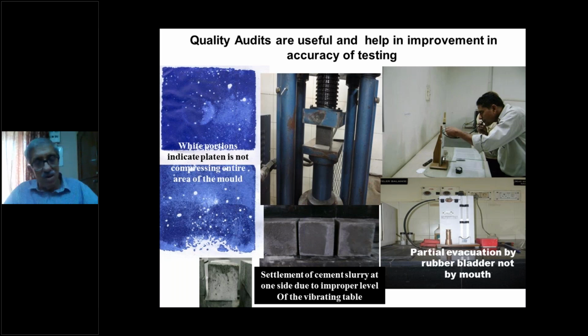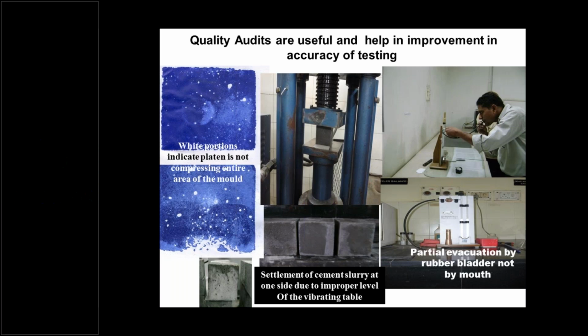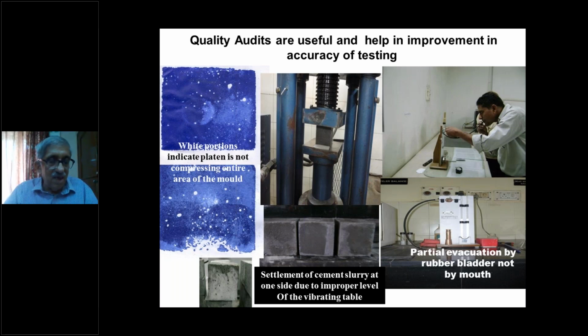You put a white paper on top of it, you put a carbon paper, both at the bottom of the cube and at the top of the cube, and then gently press the cube manually. Again, open up and see the impression on the carbon paper. You can see here on the right hand side, on the left hand side, there are some white marks and there are some big white marks also. This shows that the platen is not uniform.